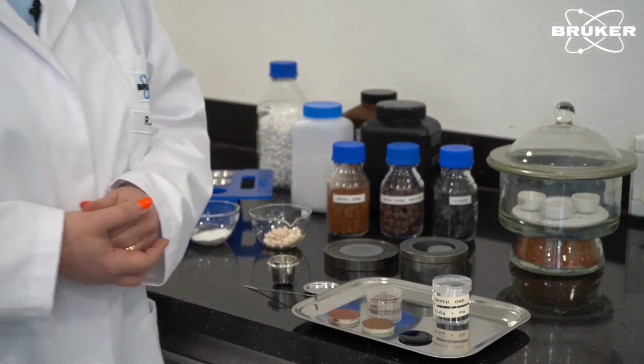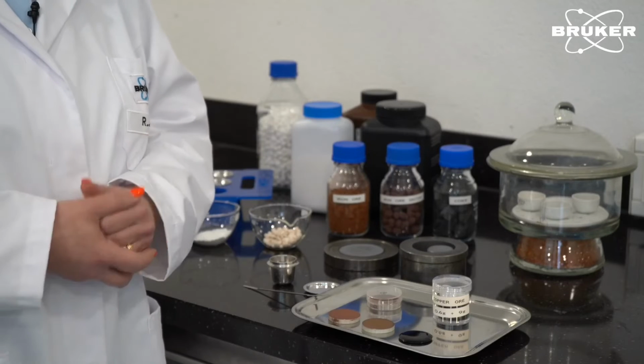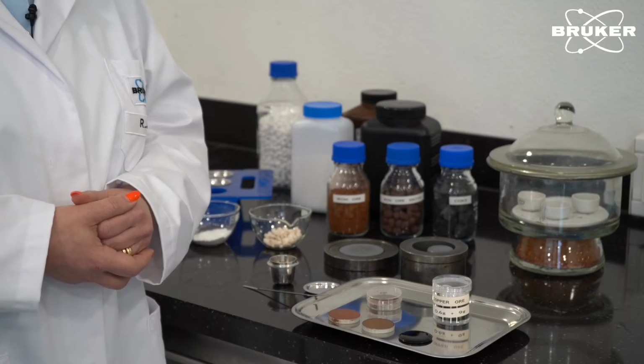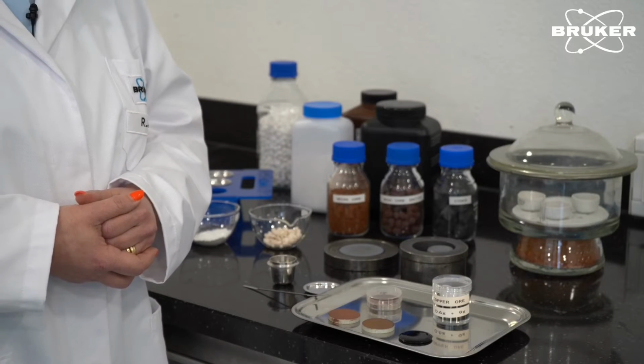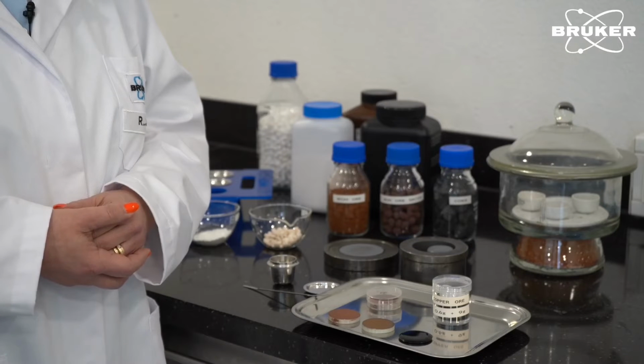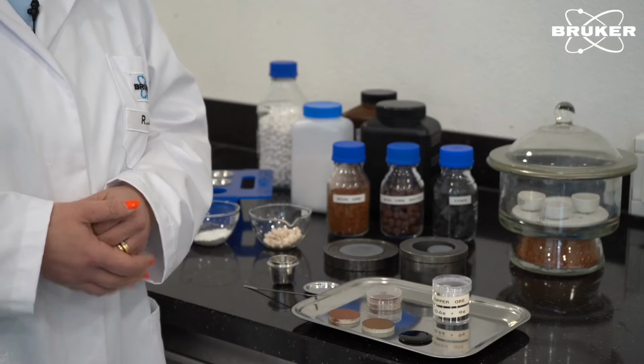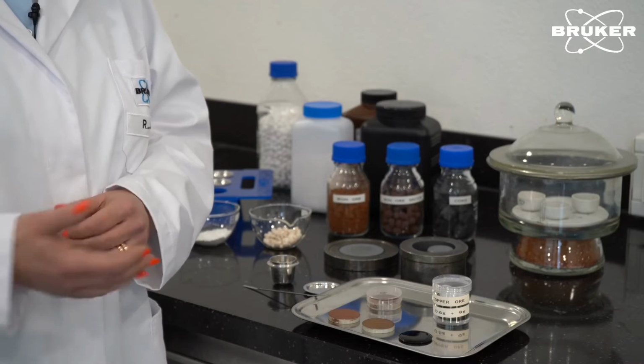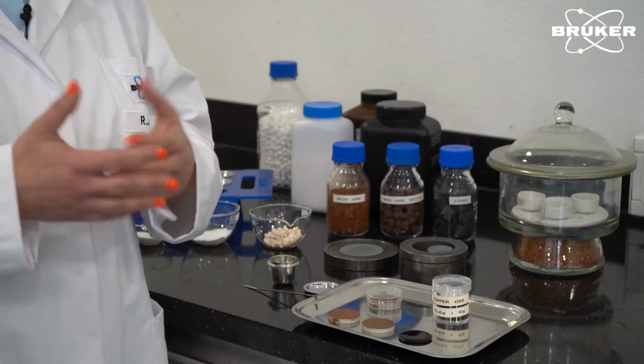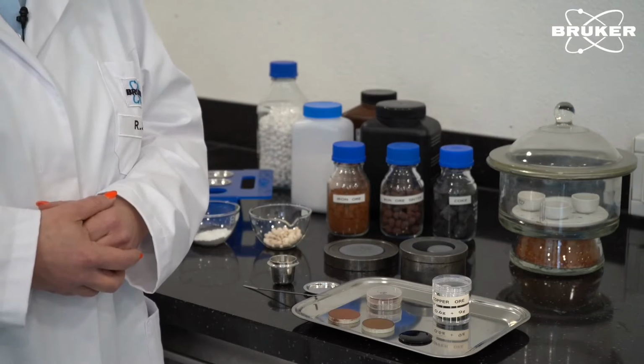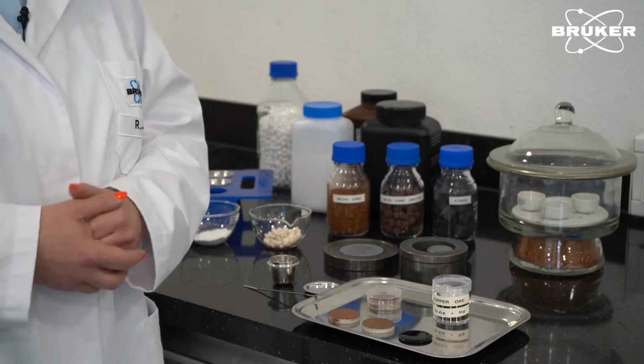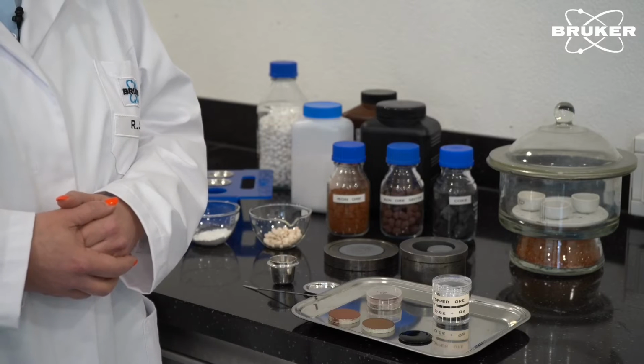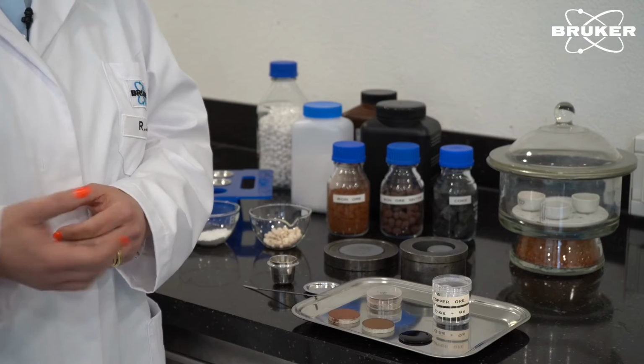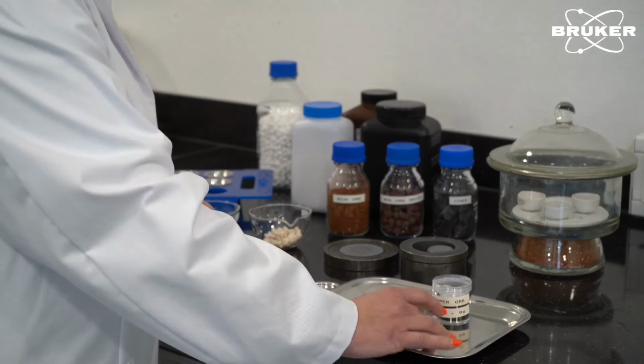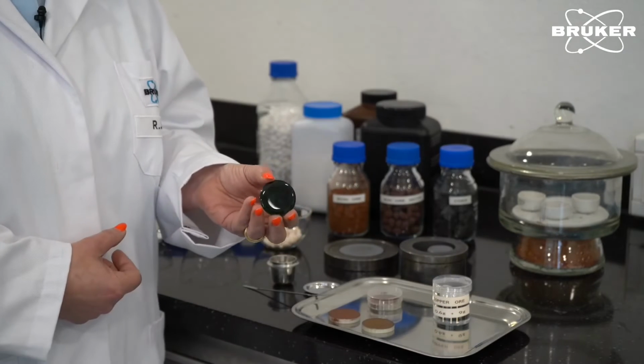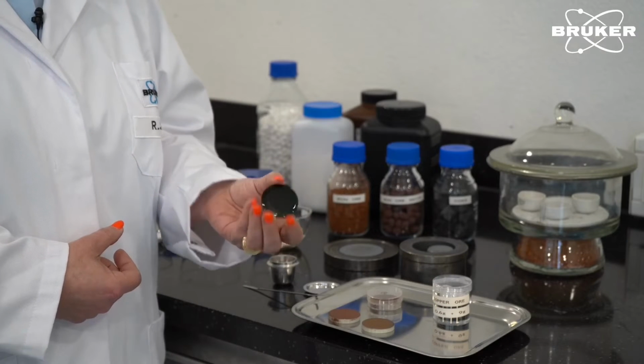Pressed pellets are very easy to prepare, they're not as time consuming as fused beads, and also the costs are lower than for a fused bead preparation. But the big advantage is the mineralogy. So especially from the beginning of the process, you will have different mineralogy. If you have samples from different sites, this will mainly affect your analysis. So in this case, for example for big labs, or if you have a central lab, then typically fused beads are prepared. Here, for example, we can see a very nicely prepared fused bead, which is a copper ore.